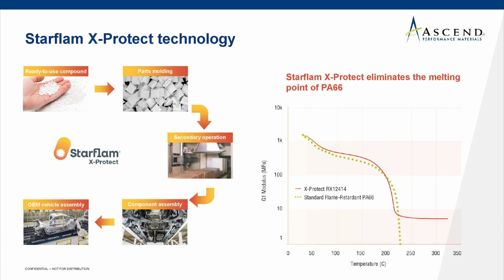We're looking at a plot of the dynamic modulus measured in a dynamic mechanical analysis, or DMA, and we plot this modulus over the temperature. The green dotted line shows the behavior of a regular flame retardant PA66, unreinforced in this case. So we start with a modulus of about 1000 megapascal. We're losing a little bit of that modulus as we go through glass transition temperature around 50, 60 degrees C. And then we see a very significant drop of that stiffness as we approach the melting point, even to the extent that we can't measure a mechanical stiffness anymore at around 230 degrees C.